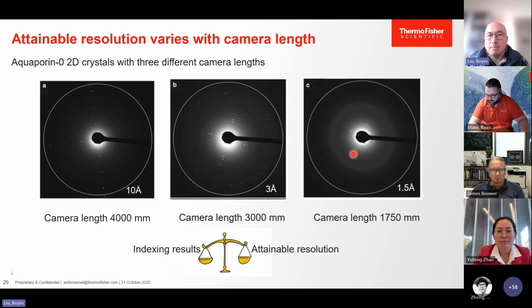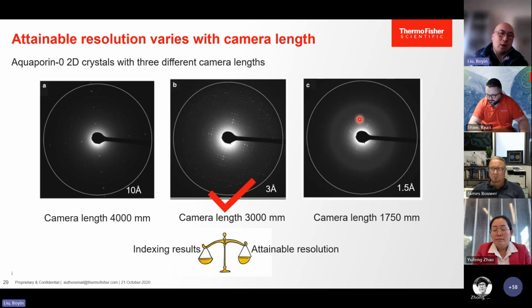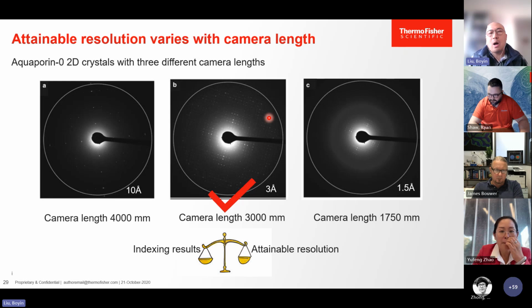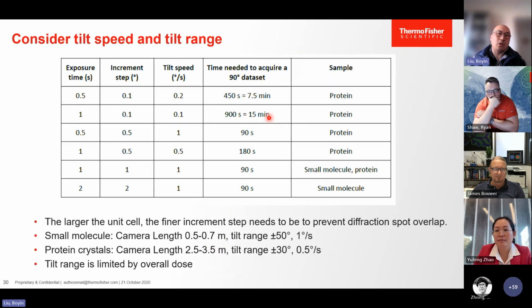but all the diffraction spots are squeezed into a very small area. It's going to create some problems with indexing later. So the camera length is all a balance between the indexing results later and the attainable resolution. For example, in this sample, for 3 angstrom, 3,000 millimeters is a good compromise. So you need to decide the camera length for your own sample. And another thing you need to consider is the tilt speed and tilt range.